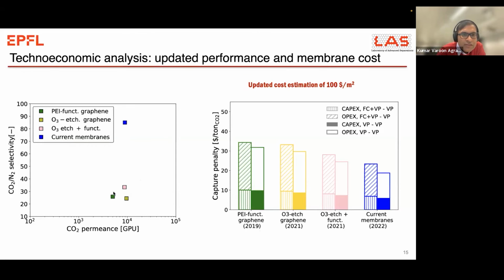What I have here is different generations of the membrane that were prepared in our lab. The green one is the first generation, then second generation, third generation, and this is the latest generation that we have in the lab. Essentially, what we have been able to show is that by changing the porosity, by optimizing the pore size distribution, and by also functionalizing these pores with nitrogen, you saw in Professor Queen's presentation that using nitrogen atoms in carbon can help improve the selectivity. We do the same thing also on the atom thick film. We were able to improve our performance, which is expressed in terms of selectivity and permeance.